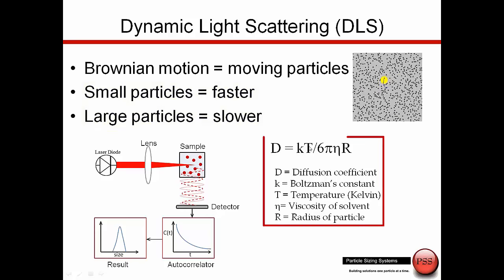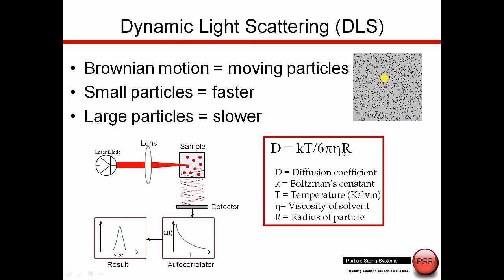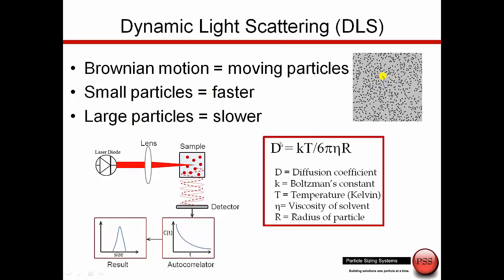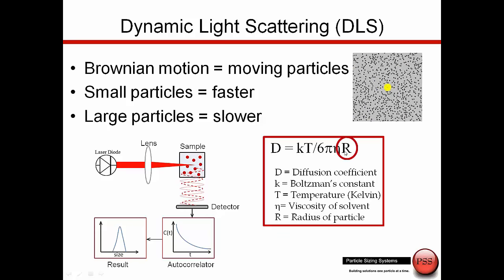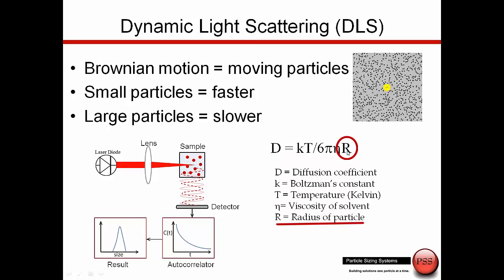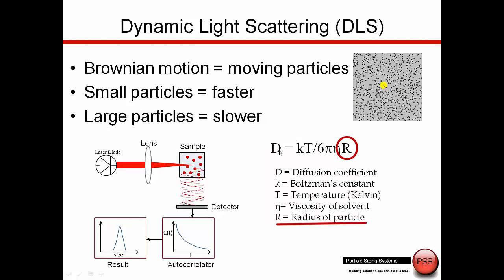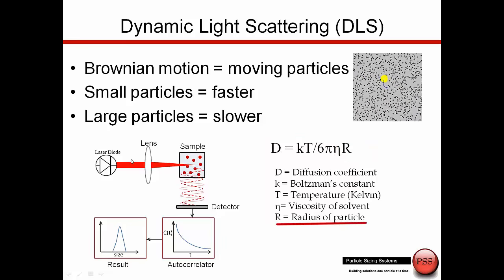So if we fix the temperature and we know the viscosity, we can then, when we determine the diffusion coefficient, calculate particle size using the Stokes-Einstein equation.